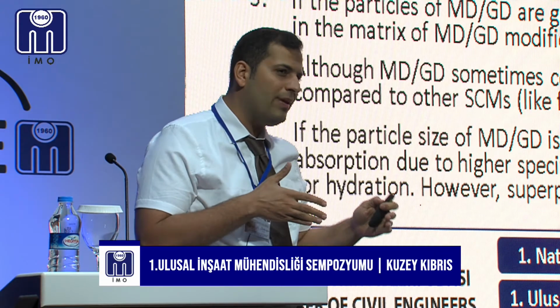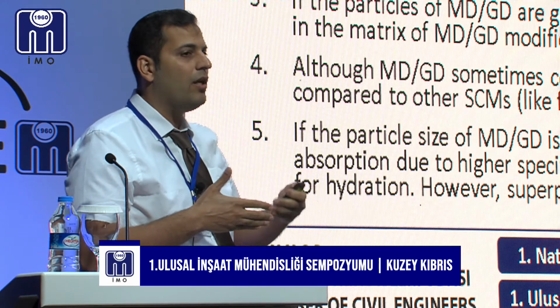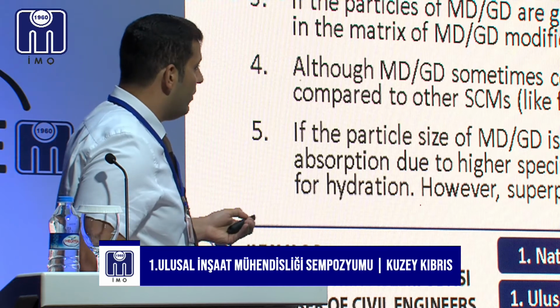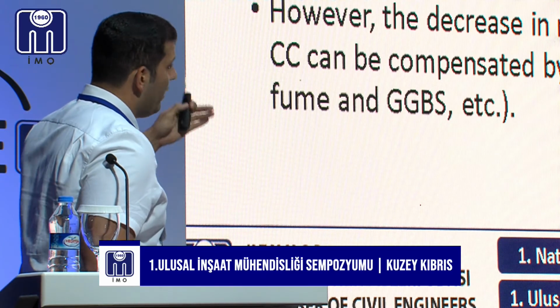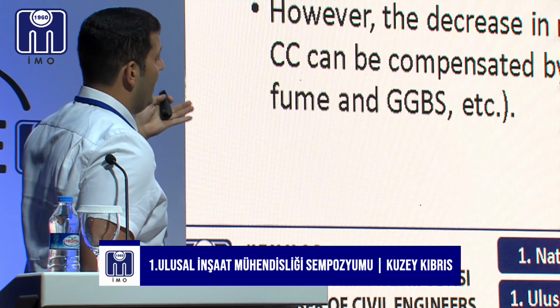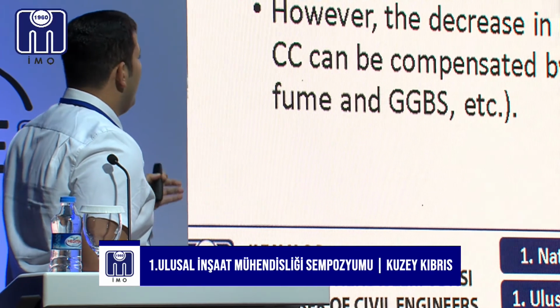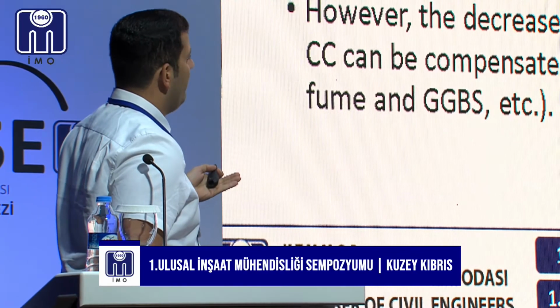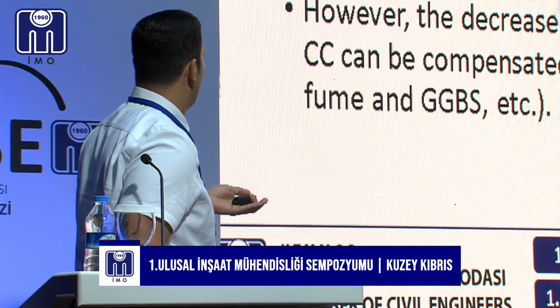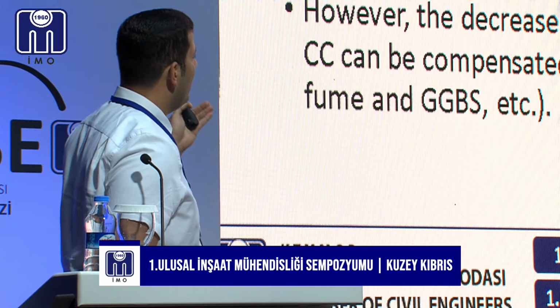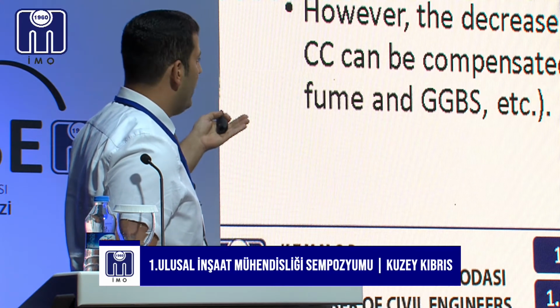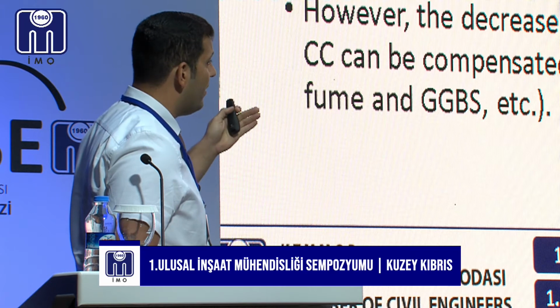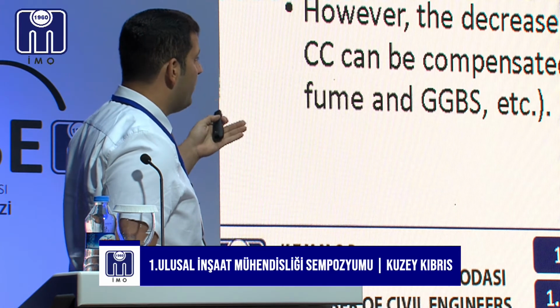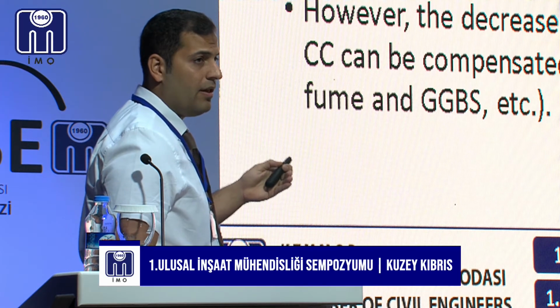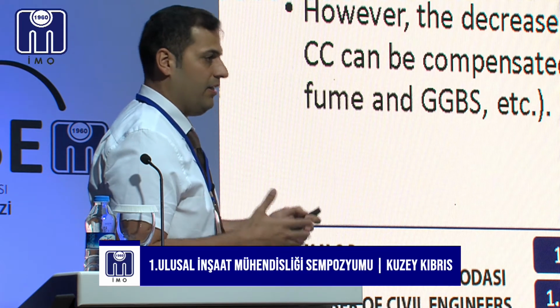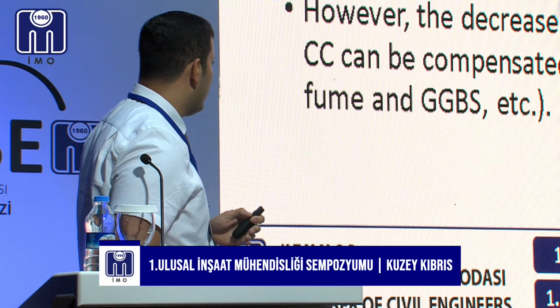However, the decrease in mechanical property is not so highlighted that we would say, okay, we are not going to use it. Still, it will be applicable when we want to use this material. In summary, for the mechanical properties, I would like to mention that the addition of marble granite dust as a cement replacement in CC can be both detrimental and effective for the mechanical properties of cementitious composition depending upon various factors. These factors are the particle size of the marble granite dust, addition of other SCM, which is very, very important, water to binder ratio, addition of the superplasticizer, and the source of the marble and granite dust. Because based on the source, the chemical composition might be different, and it might affect the hydration rate of our composite.